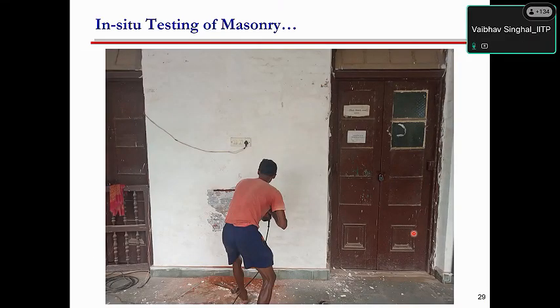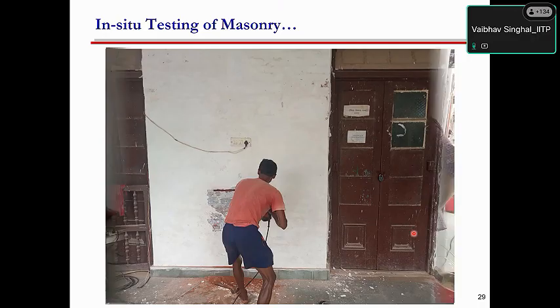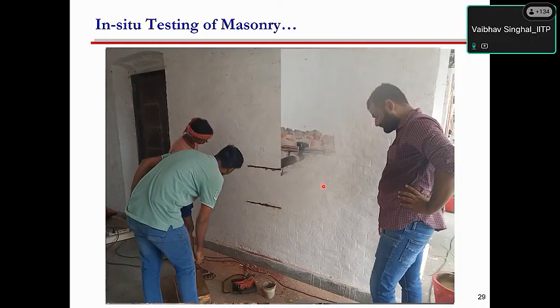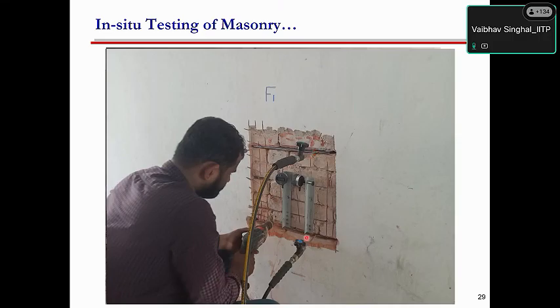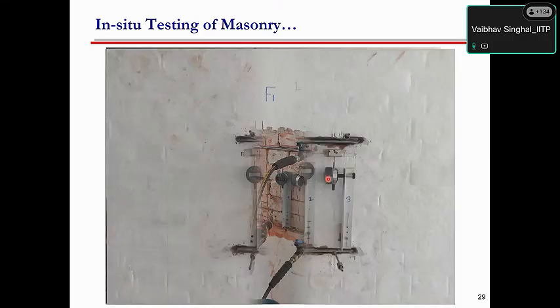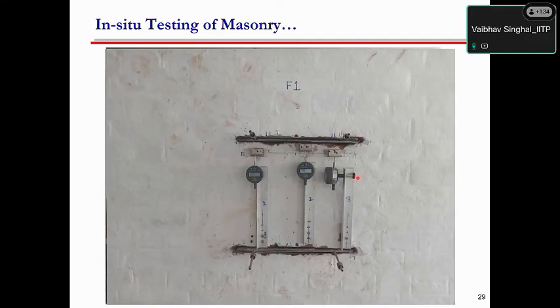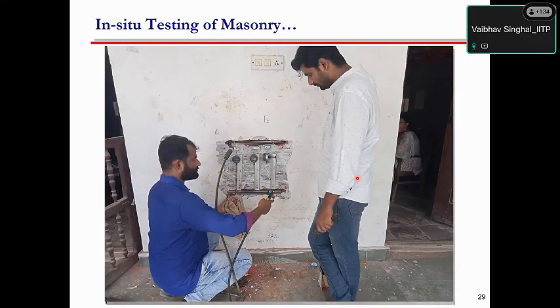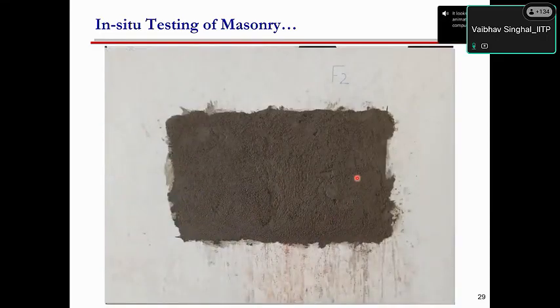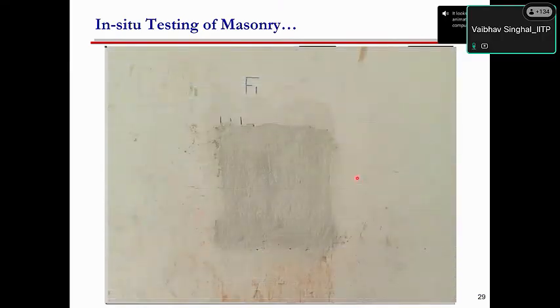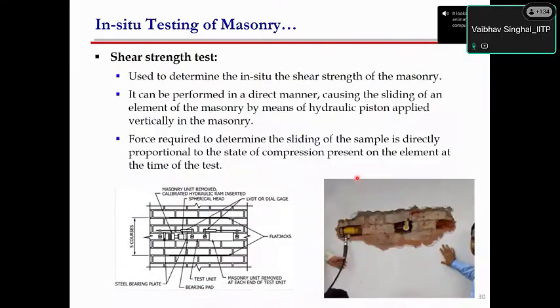So these are some of the photographs from an assessment we recently did along with the state government of Bihar. Cutting the slots, you can see here how the slots were cut, then inserting these flat jacks, placing the dial gauges. This is how the dial gauges have been placed, and then applying the pressure. And then after the testing, you can seal it and nobody will know you have done some test there. So the flat jack test can give you primarily the compressive strength and also the elastic modulus, which is required for designing and for modeling purposes.